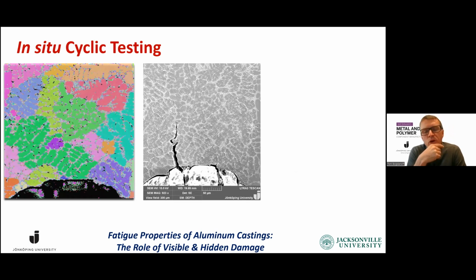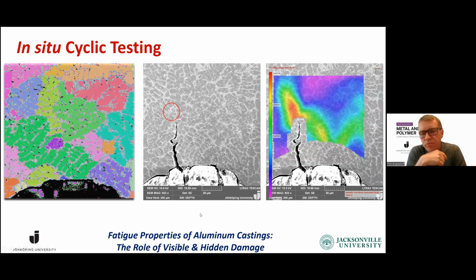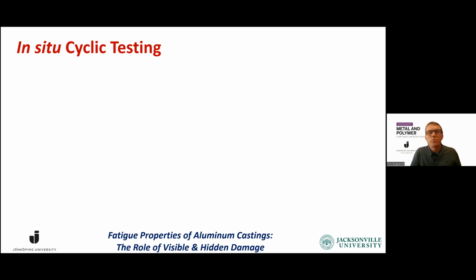We can also follow the crack propagation in real time. And in this case, we can actually see in front of the crack that something is happening. All this small pattern is made by the FIB, so we can actually follow the strain concentration. So in this case, we are also using MatchID to actually see where the strain concentration is highest. So if we link all this data together, we can actually investigate what is happening in front of the crack. So what we see here is that we had a clear crack, and that something is opening up in front of that one.